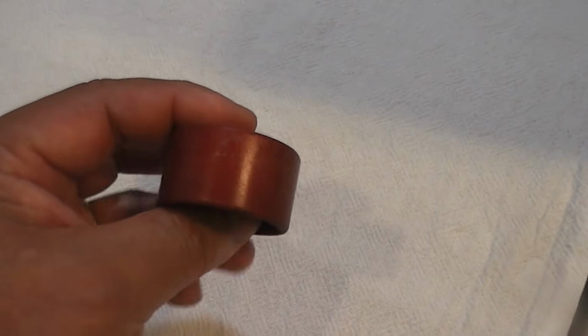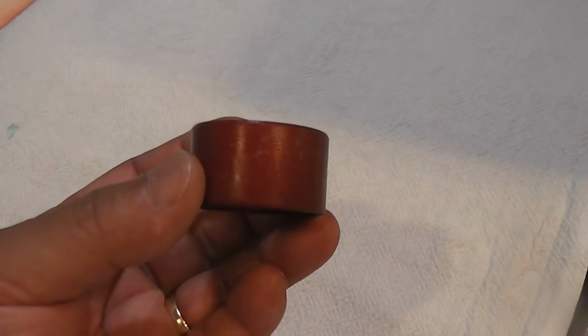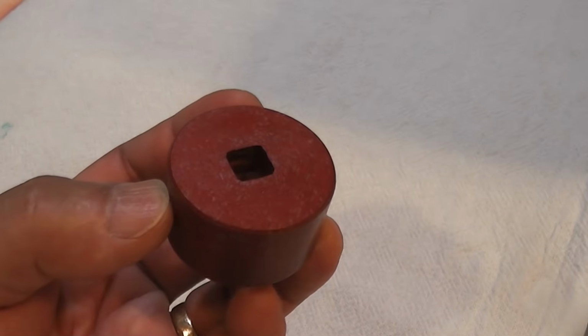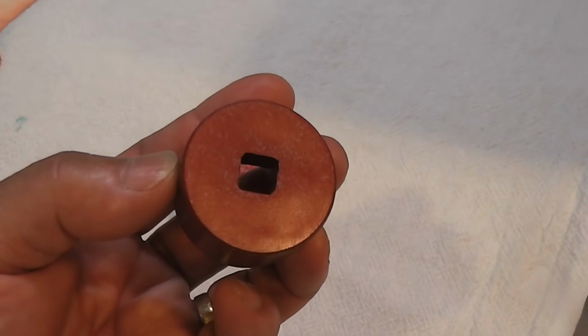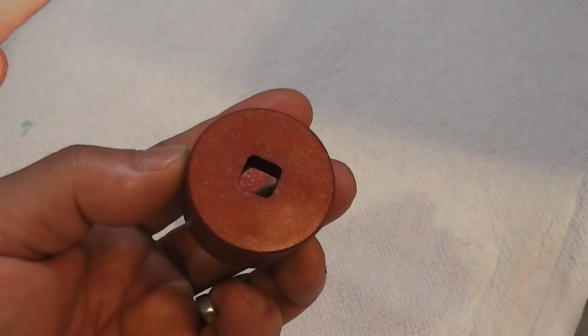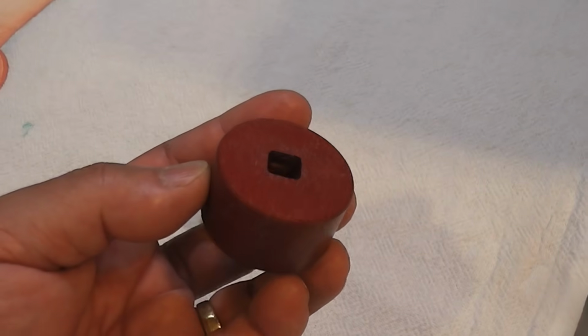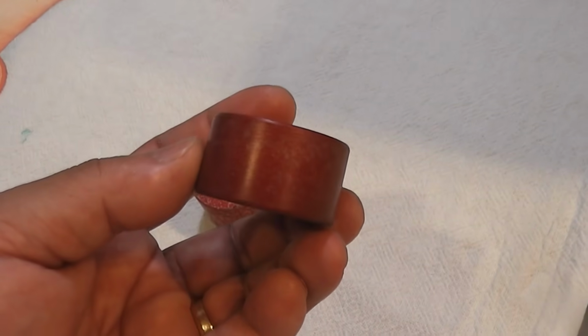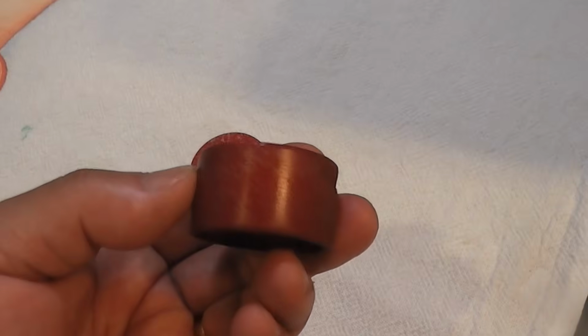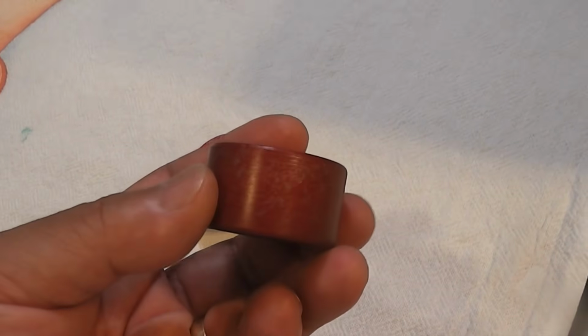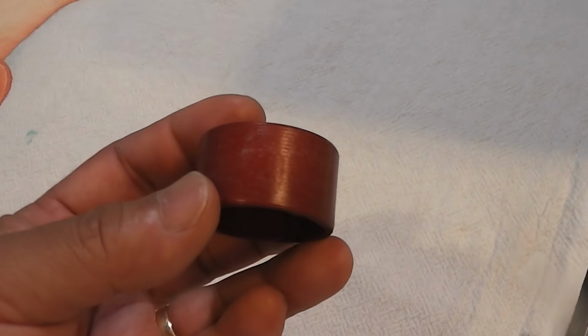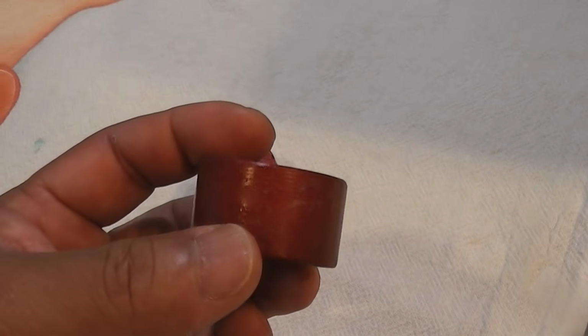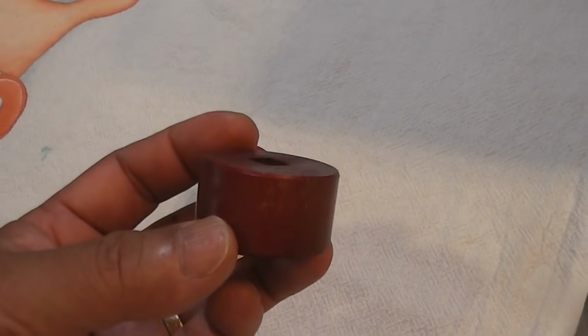For the second socket, I changed only one thing. Every 5 minutes, I gently agitated the part inside the electrolyte. This simple movement released the trapped oxygen bubbles before they could remain attached for too long. Fresh electrolyte was then able to contact the entire surface continuously. The difference was immediately obvious. The second socket showed far fewer white spots, much more consistent color, and a noticeably more uniform finish.